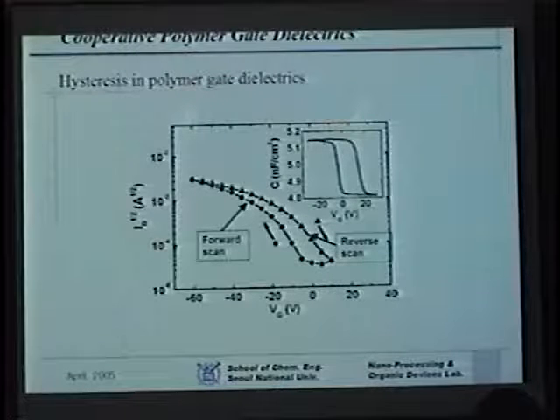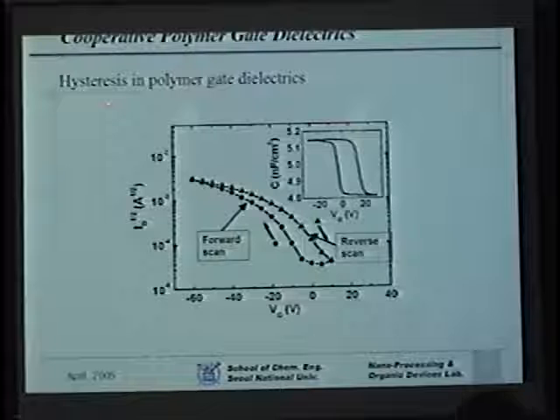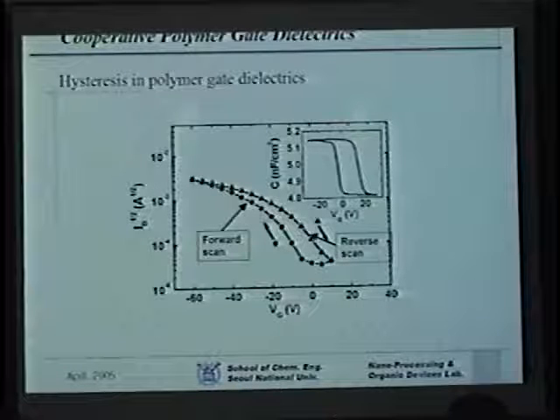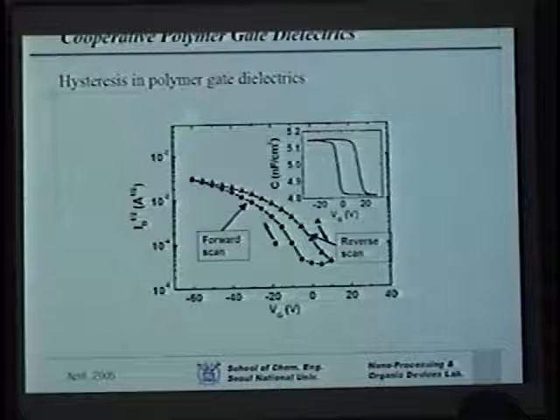So which brings us to our efforts in this area. One of the things that we tried to accomplish was to see how we can eliminate the shift in the threshold voltage, or hysteresis. Shown here is a typical ID curve you get when you do the bias scan from reverse to forward. You can see there's a hysteresis. And if you have this kind of device, you just can't use it for any practical purpose. So this has to be eliminated. The same is shown here for the capacitance versus voltage.